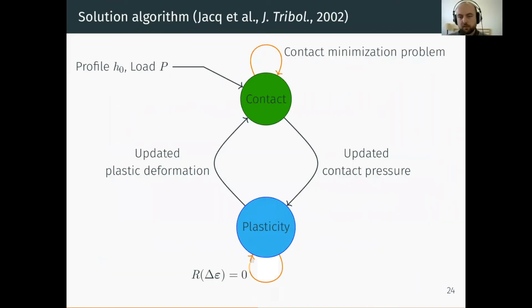Finally, if we put everything together, there's two parts in the elastoplastic contact algorithm. There's a contact part, which is basically elastic contact. It assumes that the plastic deformations are constant, and it iterates to find new contact tractions. When we converge here, we can send our updated contact pressure to the plasticity problem, which is this root finding problem. Once we've converged for this, we have new plastic deformations which inform our contact problem, and we go on and on like this until we've reached convergence.